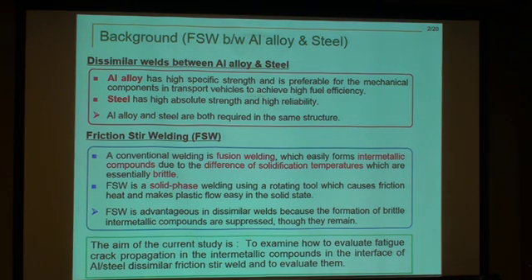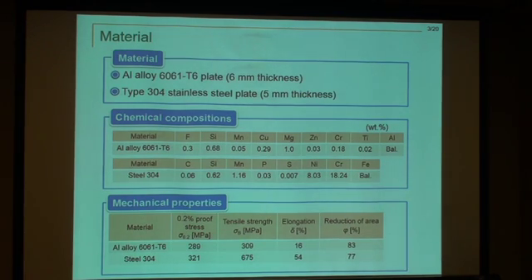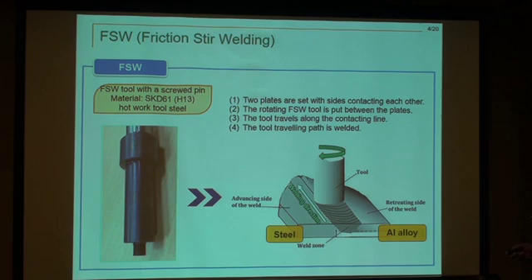The aim of the current study is to examine how to evaluate the fatigue crack propagation behavior in the intermetallic compounds in the interface of the aluminum and steel dissimilar friction stir weld, and to evaluate them. The materials used in our studies were the aluminum alloy 6061 heat-treated plate with a thickness of 6 mm and type 304 stainless steel plate with a thickness of 5 mm. And the chemical composition and mechanical properties are shown in these tables.